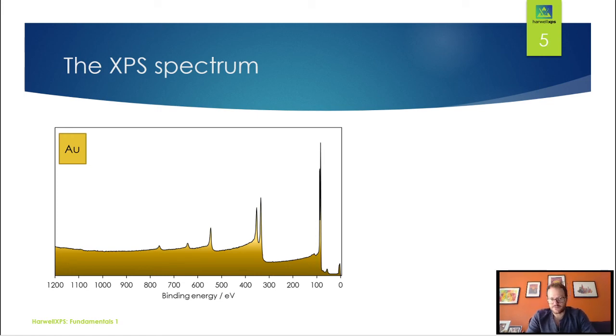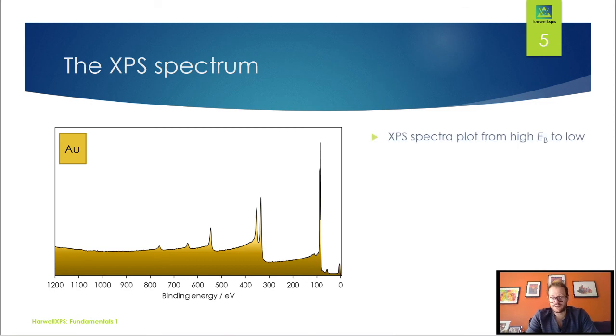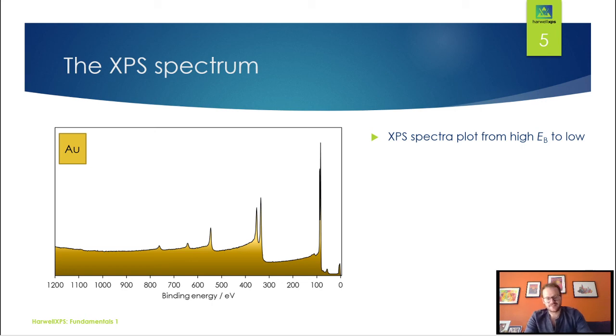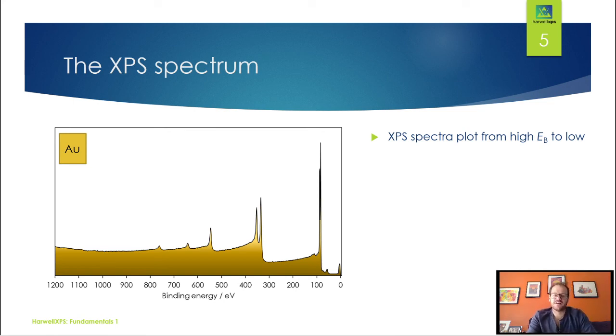We'll have a quick look at our first XPS spectrum — this is just some pure gold. It's a very nice spectrum and we can see lots of detail with quite a few peaks, not just one. That's because we are actually looking at electronic orbitals. One of the things you'll notice first is that on the X axis we're going from high binding energy to low. This is a legacy factor: XPS spectra used to be processed in terms of kinetic energy, and when converted to binding energy the direction was kept consistent. So now we plot from high binding energy to low — whenever you are presenting your XPS spectra, just remember that the X axis is reversed.